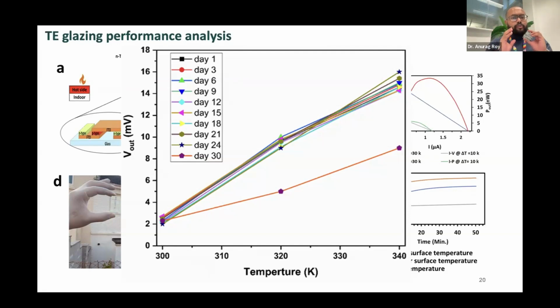That's it. We don't need to go for the traditional thermoelectric materials like tellurium and bismuth, which are good, no doubt, but the problem is we can't use them for environmental applications because of their toxicity and also the high price and scarcity. So considering every factor together, we decided to go for copper and zinc oxide, which are quite environmentally friendly and not so expensive, and that is why there is a little voltage drop. There is another factor in the voltage drop: as you may remember from a couple of previous slides, I mentioned there is a defect. So the point defect is very important here.